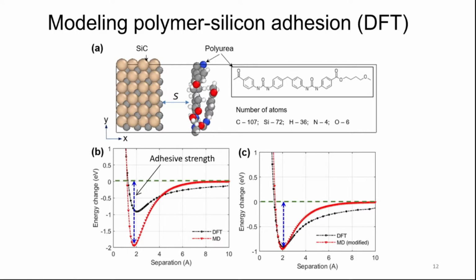The energy change with the separation obtained from DFT calculation is given in this figure in black. The energy separation curve obtained from an existing MD force field is shown in red, and the adhesive strength given by that force field is about twice the strength given by DFT. We appropriately modified that existing force field so that it reasonably agrees with DFT, as shown in figure C. We observed that the adhesive strength has a significant influence on the energy dissipation mechanisms of nanoscopic multilayers.